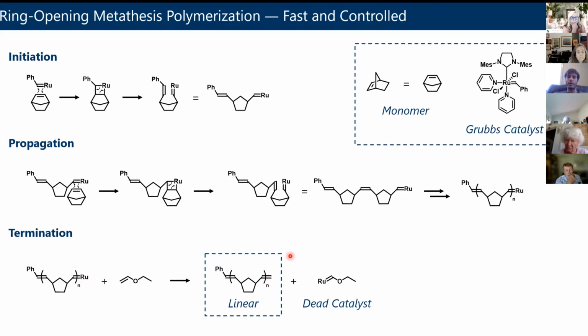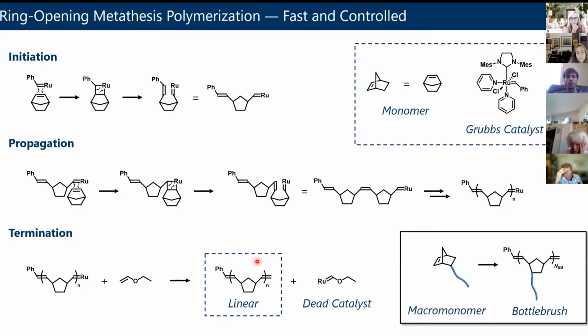But what we've depicted is growing a linear polymer chain when we start with norbornene. So how do we grow a Bottlebrush polymer, which will make super soft elastomers? We simply start with what's called a macromonomer instead of a monomer. So we take a polymer chain, which is going to become the side chains of our molecule, and we install a norbornene on exactly one of the chain ends. And then we take these macromonomers and we expose it to the ruthenium catalyst. And now every repeat unit has this starting polymer chain, and the ruthenium builds up the backbone by polymerizing these side chains together over and over and over again to some degree of polymerization or length that we call NBB for the backbone.